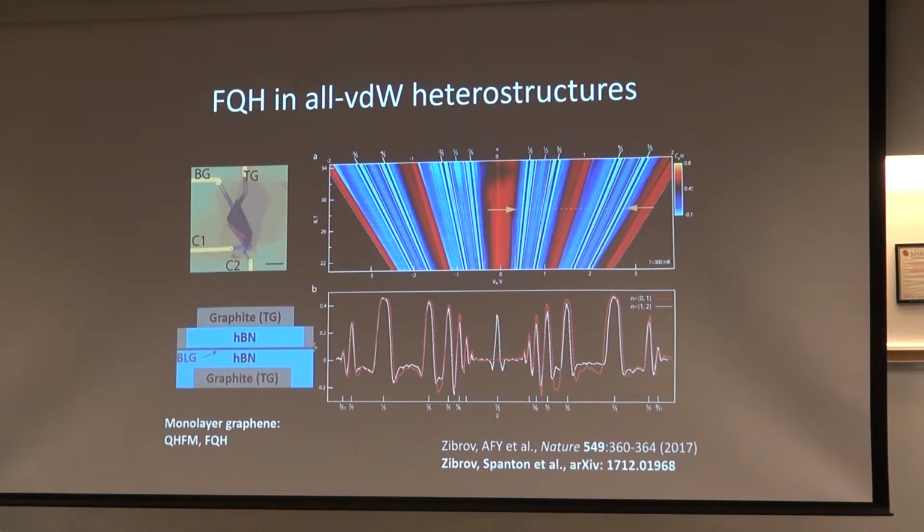Fast forwarding, in keeping on the direction that we ended up in, if you can remove that silicon oxide substrate and replace it with something that doesn't have the same density of charge traps, then you can improve on that. So hexagonal boron nitride was kind of the solution to that. Hexagonal boron nitride has the same crystal structure as graphene, but it's an insulator because boron and nitrogen have very different energies.